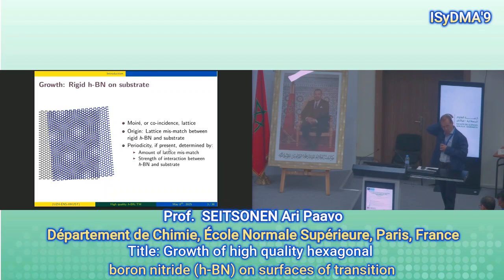And then when you grow these things on surfaces, so this is the rigid layer on a surface, and if the lattice constant does not match the lattice constant or the nearest neighbor distance of the substrate, there's usually this thing called moire structure which appears. Maybe you are familiar with this. One example is similar to what is shown on the left. If it's 2 layers of graphene, if you have this magic angle, you make it superconducting. So you have a bilayer of graphene and you make it superconducting because you have just the right angle between those two. And now here the difference comes from the different lattice constants of the HBN and the support.